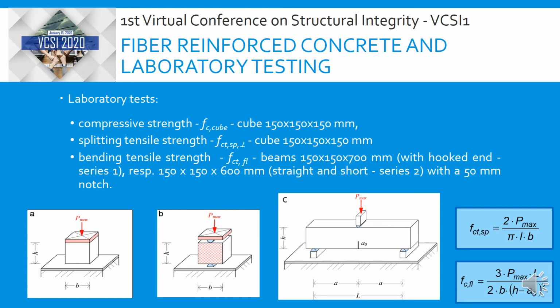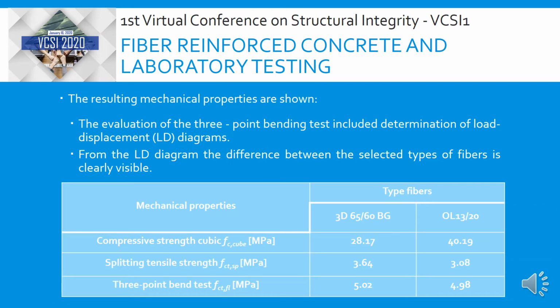Laboratory tests include compressive strength for cube, figure A, splitting tensile strength for cube, figure B, and bending tensile strength, figure C. Beams for the bending test each have a 50 mm notch. The resulting mechanical properties are shown in the table. The evaluation of the 3-point bending test also includes determination of load displacement diagrams. LD diagrams were used for numerical modeling.